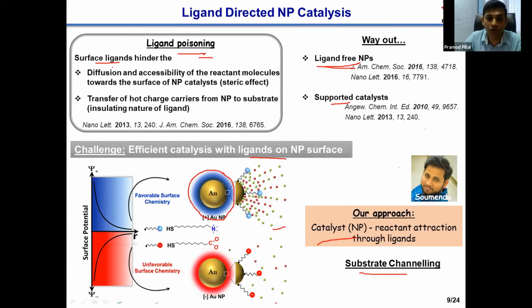For example, if you are working with a negatively charged substrate, and if you can make positively charged nanoparticles, because of the strong electrostatic attraction, all the negatively charged substrates, or reactants, will be attracted towards the surface of the nanoparticle, and this will help in improving the catalysis. So this is the simple hypothesis that we came up with, to decorate the nanoparticle with appropriate ligands. Now we want to test this hypothesis in the area of catalysis.